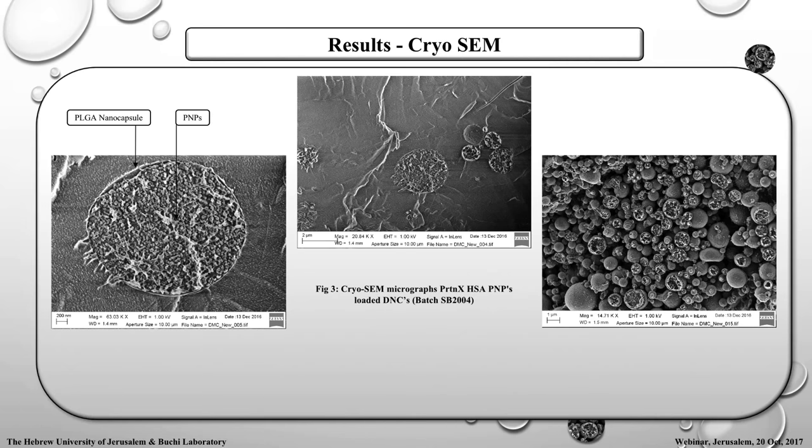Apart from that, as I said, we tried to determine whether our platform technology works or not. So we tried to identify whether PNPs have been incorporated inside the double nanocapsules, and we did this by using cryo freeze-fracture SEM. We can easily identify here in the bigger picture that most of the PNPs are inside the double nanocapsule, which is made up of PLGA. In the image on the right-hand side, many particles have been cut open during the freeze fracture and can be easily seen here, with the PNPs. So the technology we are using works, and it helps to encapsulate macromolecules inside the PLGA